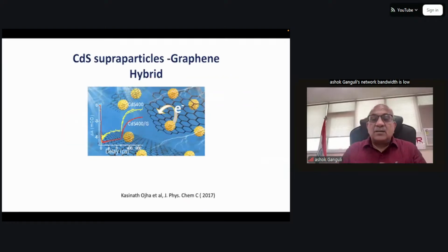This is another example of if I have an electron sink in the lattice. Suppose I have some semiconductor particles. Here we have got cadmium sulfide supraparticles, which are like balls of 5 nanometer particles assembled together to make 400 nanometer supraparticles. If they are put on a surface of, say, graphene oxide, it acts as an electron sink, and it pulls away electrons when they are generated by the photons falling on the lattice, right? And if the electrons are removed from the site faster, your lifetimes are high, and the electrons will be more useful for any reducing reaction or generating current. And that's the idea behind this.